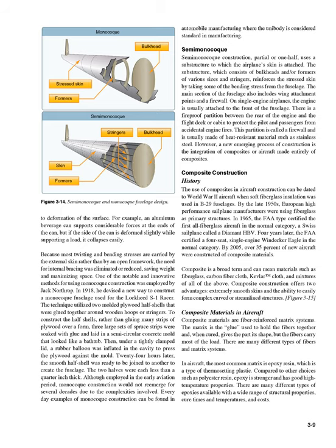Then, under a tightly clamped lid, a rubber balloon was inflated in the cavity to press the plywood against the mold. Twenty-four hours later, the smooth half shell was ready to be joined to another to create the fuselage. The two halves were each less than a quarter inch thick. Although employed in the early aviation period, monocoque construction would not re-emerge for several decades due to the complexities involved. Everyday examples of monocoque construction can be found in automobile manufacturing where the unibody is considered standard.